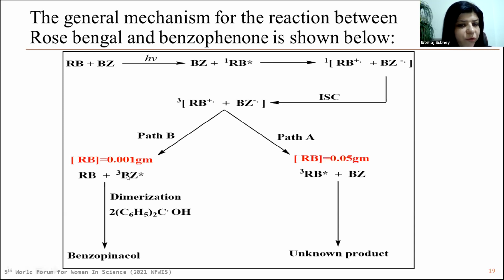At the same time, the benzophenone in triplet under dimerization converts to benzopinacol in high yield, about 86%, and reduces the time of reaction, because here the rose bengal quenches the oxygen that affects the benzopinacol yield. In this path, when we increase the concentration of rose bengal to 0.05 gram, the benzophenone does not react, we don't see benzopinacol, we can isolate benzophenone and detect it by melting point. Here the rose bengal is converted to an unknown product because we see a change in color in the reaction. This means a change in the structure of rose bengal maybe happens.